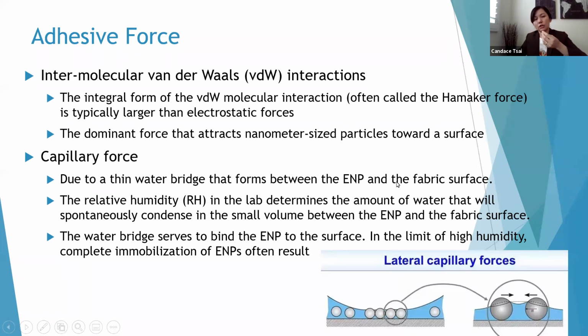Under a high humid environment, the nanoparticle and the surface of the fabric can form a water bridge because of the water molecule in the air. That water bridge can form like a trapping bridge to adhere the nanoparticle onto the surface, and also make nanoparticles stick to each other if they are a hydrophilic type. These are the 2 major forces dominating the surface interaction for the untreated surface.